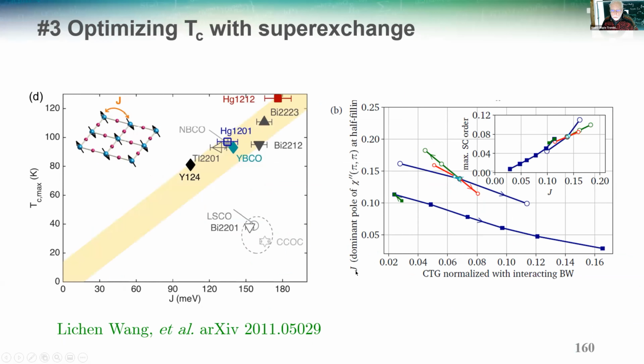You see super exchange J now, as we measure in this calculation, as a function of the charge transfer gap. And you see that the J here is inversely proportional to this charge transfer gap for both models, the covalent and the ionic model. Now, this is not surprising, because if we go back to this J equals 4T squared over U, we see that we just replace U in the one-band Hubbard model by the charge transfer gap, and then we get basically this inverse correlation. Qualitatively, obviously, I'm not claiming that it's exact.